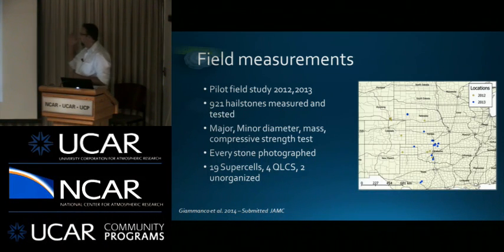So in terms of if you were just going out and measuring hail diameter, you could probably do thousands of stones. But over 2 years, we're just now to that 900 mark, and I think we pushed it over 1,000 with a case this year. So we measure the major and minor diameters, we weigh each stone, and then perform the compressive strength test. We also photograph every single hailstone, so we actually know what the layering structure looked like to see if.